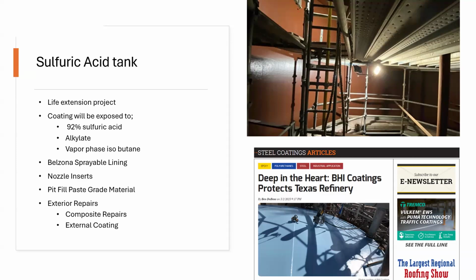Some pitting at the manway, and it also had some through wall defects at the manway as well. So we did some external repairs, but on the inside we coated it with a two component epoxy liner that can handle everything in the tank from the 92% sulfuric to the alkylate. It was a sprayable liner, and then the little details.